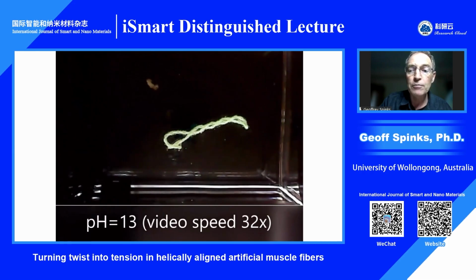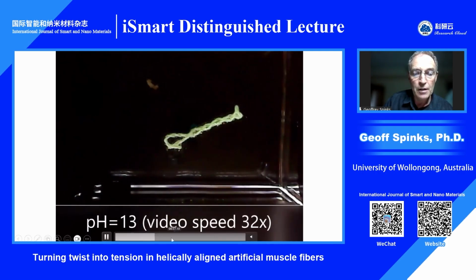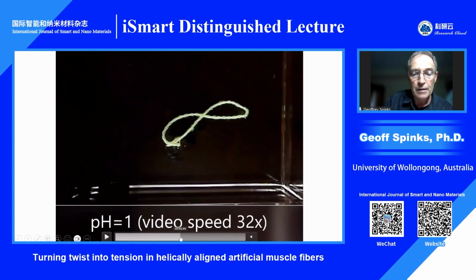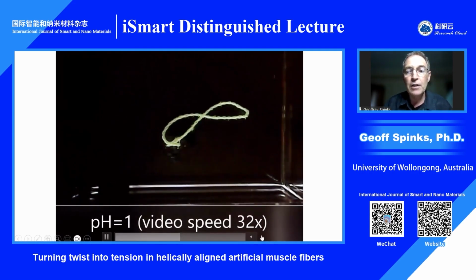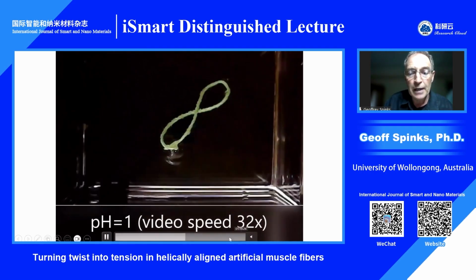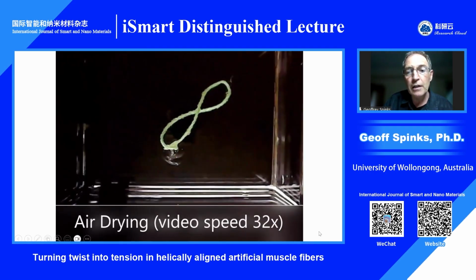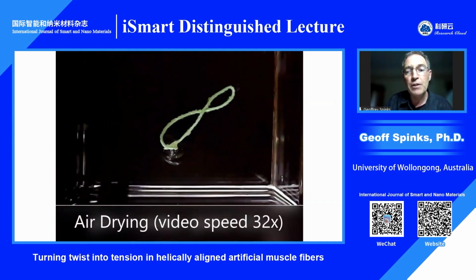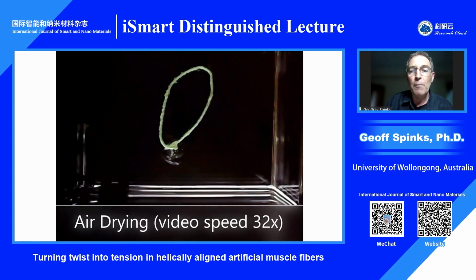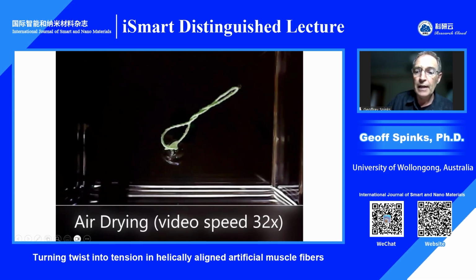It plies around itself to relieve the torsional strain that's being generated by swelling. I'll just show you what happens when we put it back into acid. It untwists, it unplies itself, and from that point on, we can then air dry to further shrink the volume of these composite yarns, and you'll see it starts to then ply up in the opposite direction as the yarn actually retwists, increases its twist, or wants to, and to do so, to relieve its torsional strain energy, it has to ply around itself. So there's a first example of supercoiling.